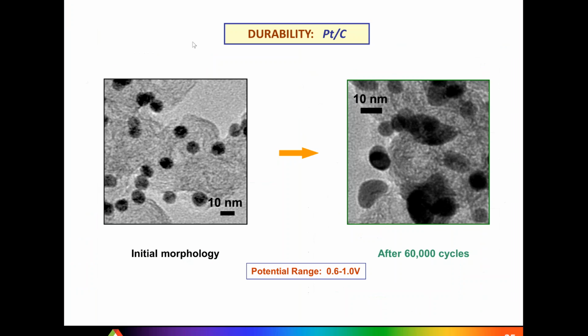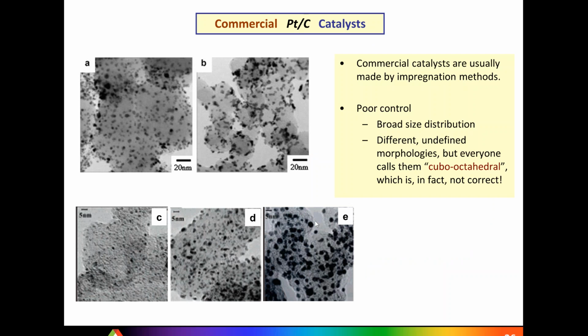So we all know when we mention durability of platinum carbon catalyst that morphology before and after is substantially altered. So after a number of potential cycles, we are losing electrochemical surface area. We do see agglomeration, and the catalyst is losing performance. But this is something which I always like to show. However, this is not how a state-of-the-art platinum catalyst looks like. So this is an example from our own monodispersed particles. So what we have in reality is pretty much, it could be confusing, it could be misleading, and I think in many cases this is the source of some wrong conclusions that we can find in the literature.